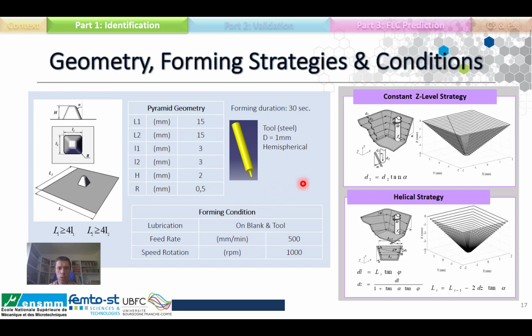And we used several trajectories. So the forming strategy chosen here is constant Z level, meaning that within one forming cycle, the tool forms the blank at a certain height until it returns to the starting point, and after that it goes one step down and follows the path for the next level, and so on until the end of the trajectory. So one forming cycle lasts around 30 seconds.